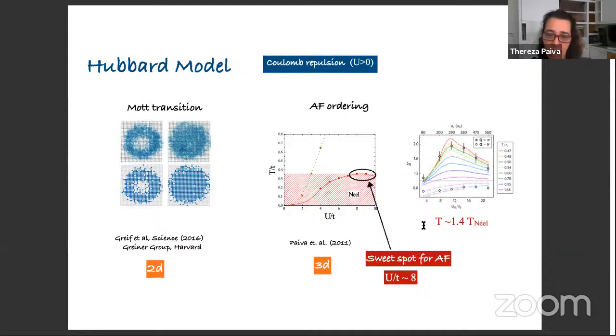But one thing I want to have in mind here is when we look at the theory for the 3D Hubbard model, and here is the temperature as a function of U. This red line here is the one I really care about at this moment. There is a maximum here. So there is a sweet spot for antiferromagnetism, which is about U over t equals 8. So if an experimentalist wants to reach the Néel state, this is the best place he should try, because the Néel temperature is higher here than it is here, and than it is on the other side. On the other side, where I have not shown the data.